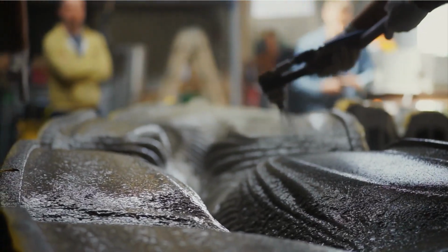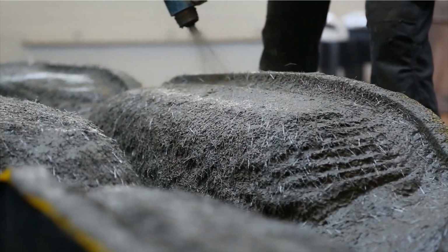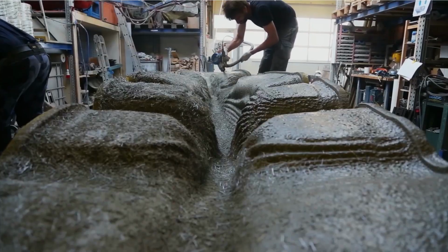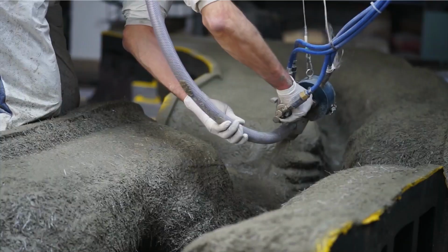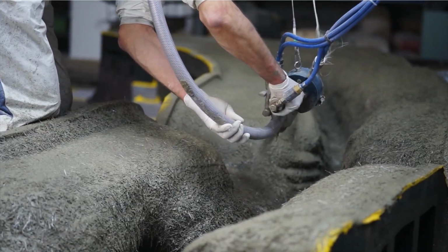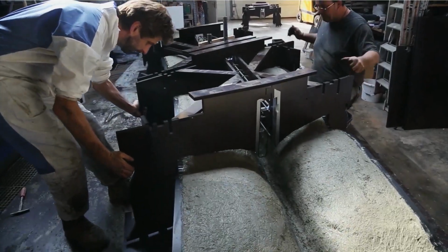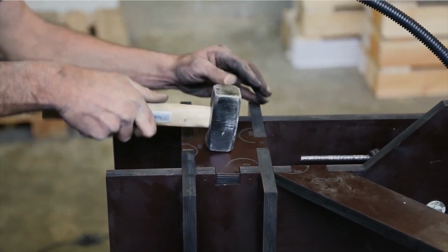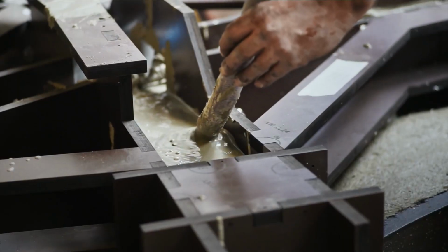The 20 millimeter glass fiber reinforced concrete was sprayed, and then the assembled wood modules were placed right on top of it. This had to be very quick in order for the concrete to have a great bond.